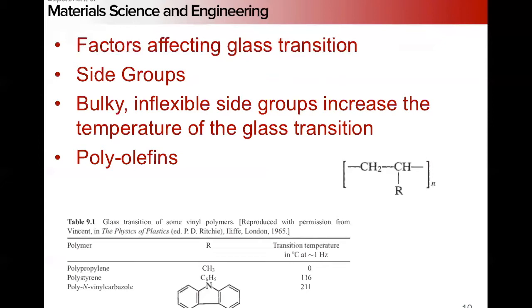So if we look at the family of polyolefins, and we look at what the side group is, if we go from a polypropylene, which has a simple methyl side group, up to this nasty looking structure here with some vinyl, I don't even know how to describe that. But we see a 200-degree change in the glass transition temperature, simply because these large molecules, these large side chains, can't get out of each other's way. That's really all what it boils down to.